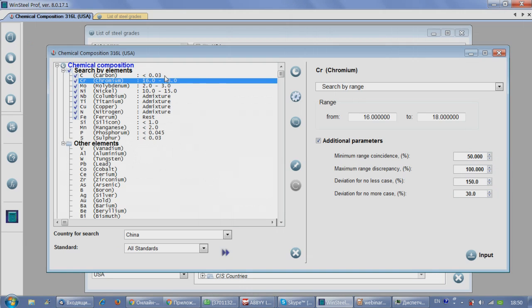the content of carbon is more close to the upper bound. So for such cases, deviation for no more case, by default, the maximum value is this one, 0.03, and minimum value is not zero. Is not zero if you use this coefficient, but 30% of this one. So in the search, it will be from 0.009 to 0.03. The same for such elements such as manganese, silicon, and so on.